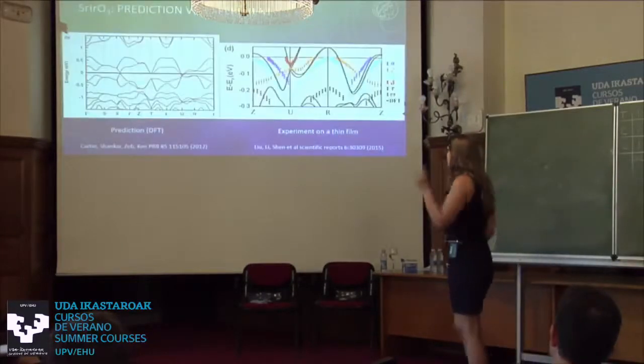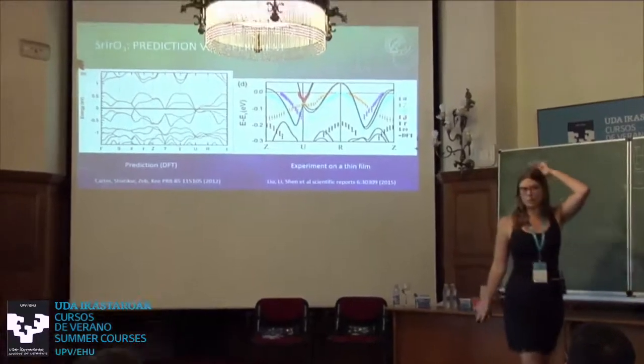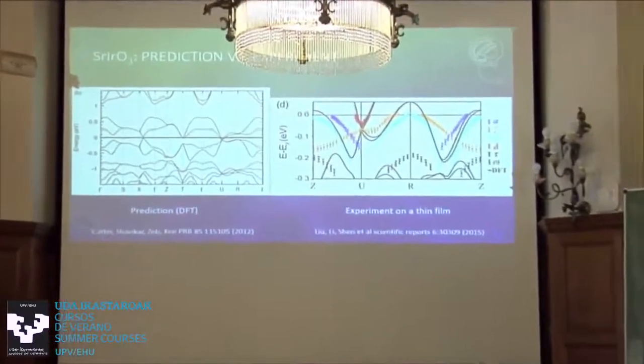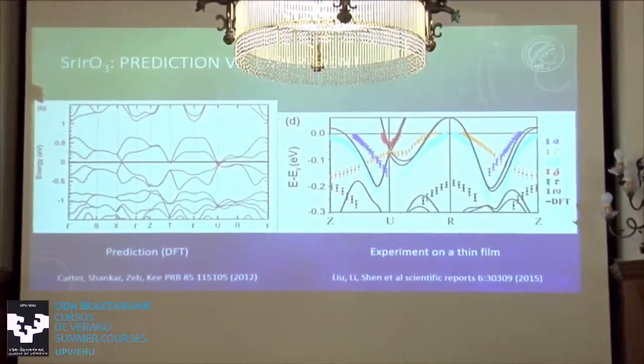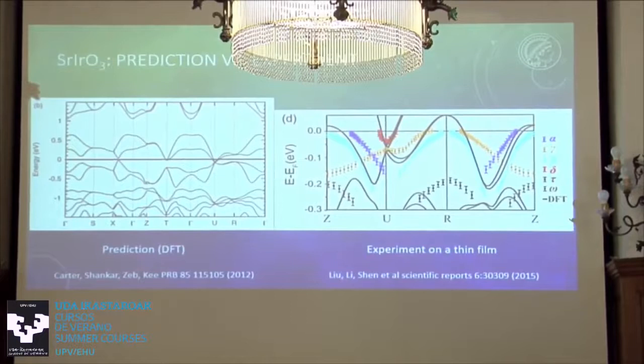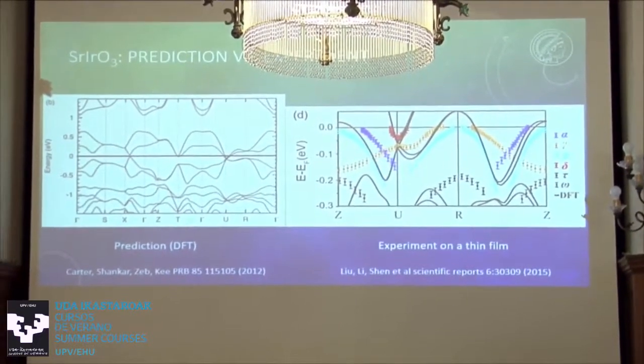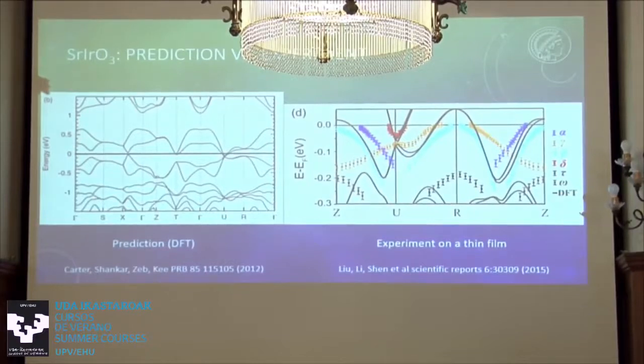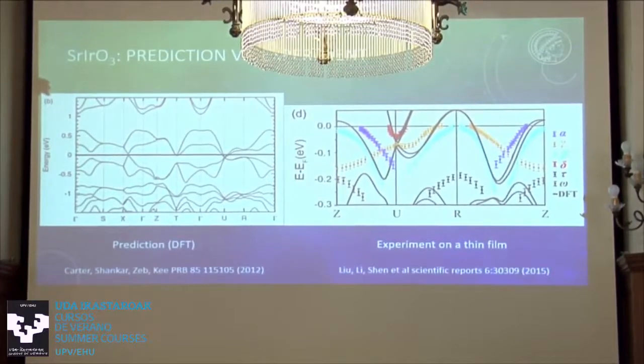And so here's an experiment where they grew strontium iridate as a thin film in this orthorhombic form. Here's the predicted DFT, where we have this nice non-symmorphic crossing at the U point. And then the colored lines are the measured ARPES, so here's the U point. And the black lines are the adjusted DFT, where they played around with spin orbit coupling and some strain to model the sample. And you see here, there's a gap. So this crossing isn't completely there anymore. Also, there are lots of electron pockets and hole pockets trying to stabilize this. So something is fishy here. Maybe the structure isn't completely correct, or maybe in the thin film it's a little bit different. I'm just saying to be really careful with what is listed there.